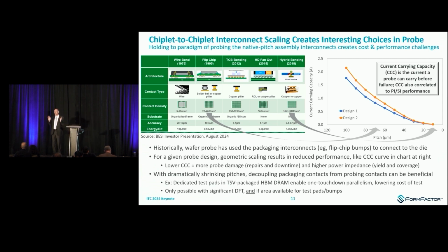Now, both of these things can be done, we'll see on the next slide. But a real economic choice. Remember, the reason people are doing probe is to screen out bad die and to have a significant ROI associated with that activity. If you build a super complex probe card that tests every bump on one of these hybrid bond devices, that's going to be really expensive, right? And so you've undone the very thing you're trying to accomplish by creating very high cost of wafer sort that may not have any ROI. Having said that, in characterization and development, there are many cases where we and our competitors do build probe cards that contact every or a majority of the hybrid bonding bumps. Again, they're just very complex, and as you can see from the CCC chart, not very robust.